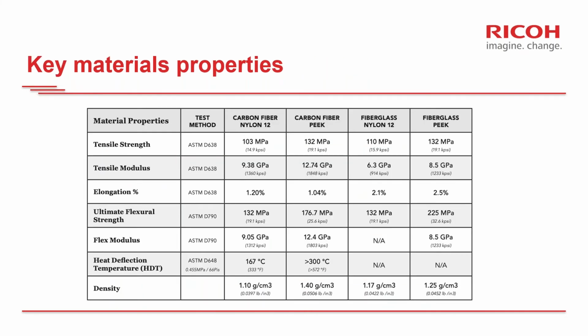And if we look now at the mechanical properties we can achieve by combining those different materials together, you can see that you can achieve parts with a very high tensile strength, which is generally above 100 megapascal for different material combinations. Parts produced with PEEK and reinforced with carbon fiber have the higher tensile strength and tensile modulus. Whereas if you need parts with a slightly higher elongation at break, of course, in this case, it is not a very ductile material that you get. So generally, parts with reinforcements of glass fiber are the best option in this case.